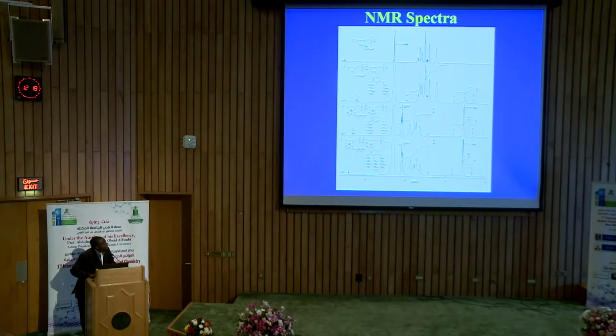This is for the amine. The top one is the experimental one, and the second one is the simulated, which matches very well with our structure. This is the NMR of the monomer, and the lower one is the simulated type, and each proton is accounted for. We also do elemental analysis. We also do IR analysis, but these are just typical examples. This is the NMR spectra of the polymer. The first one is just hydrophilic without hydrophobe. The second one contains twin tail, double tail, and then the last one is a triple tail polymer. Each one is characterized with NMR, elemental analysis, and molecular weight characterization using light scattering.